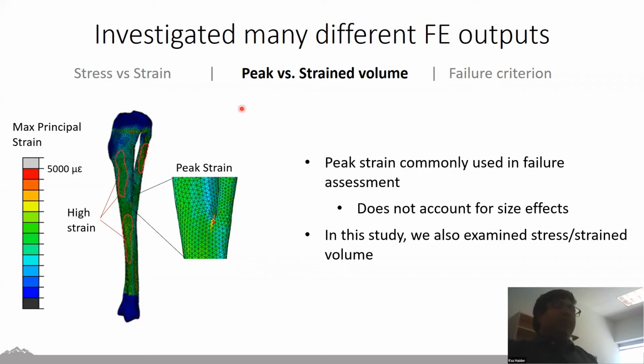So in this study, what we did was we decided to use both peak strain and strained or stressed volume measures. That is, we counted the volume of elements that were above a certain threshold.